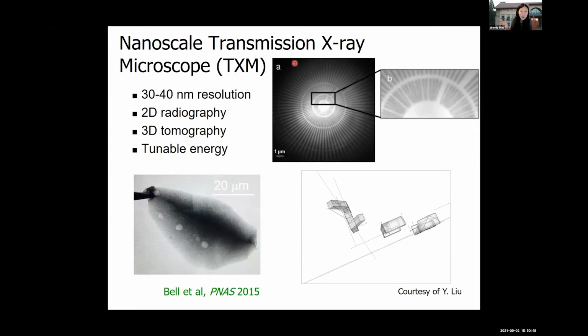It has all the same parts as an X-ray microscope, but one of the key features, especially for diamond anvil cell work, is the very, very high spatial resolution. You can do two-dimensional imaging in both phase and absorption contrast with 30 to 40 nanometer spatial resolution. This is a figure of a Siemens star calibration pattern, and the width of the thinnest lines here is 30 nanometers.